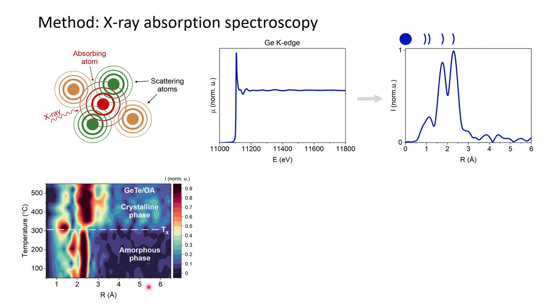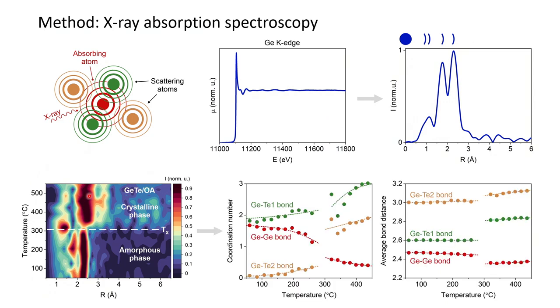Of course, we can do this radial distribution, and here you see this heat map while we heat our germanium telluride nanoparticles. Clearly, something is happening at about 300 degrees, because you see that these peaks actually change to the other one. As I said, we can calculate the number of neighbors, the coordination number, and also the distance to these different atoms, the average bond distance. And we do it for different temperatures, and these are the plots I would like to explain a little bit.